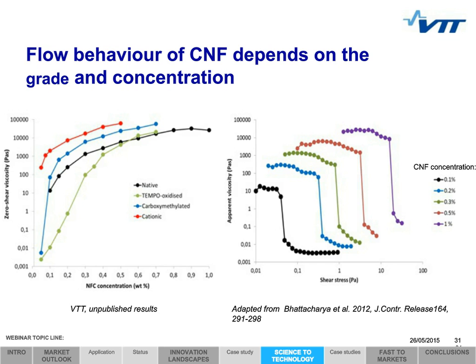The graph on the right shows that yield stress of the CNF suspensions is already apparent at consistencies as low as 0.1%, and the yield increases exponentially with increased consistency. In the graph on the left-hand side, the shear viscosity of different CNF grades as a function of concentration can be seen. The behavior of different grades is quite similar. In other words, fast increase is observed in the viscosity as the concentration increases before leveling off, but the level of viscosity between grades is different.